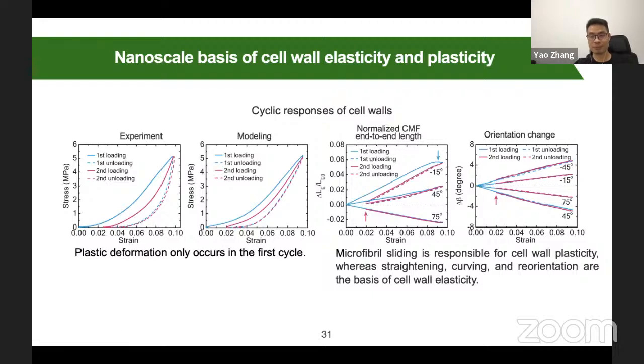So basically, this figure shows how the normalized fiber end-to-end length changes as you do this cyclic loading. So you can see that in the first cycle, this blue arrow shows that we see a plateau of this blue line. As I introduced before, once we see the plateau, it means that sliding happened. If sliding happened, it means that we generate this permanent strain. You can see that this is a plateau. Also, you can see the sliding only happened in the first cycle.